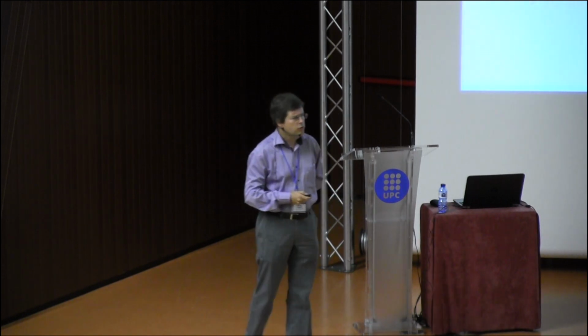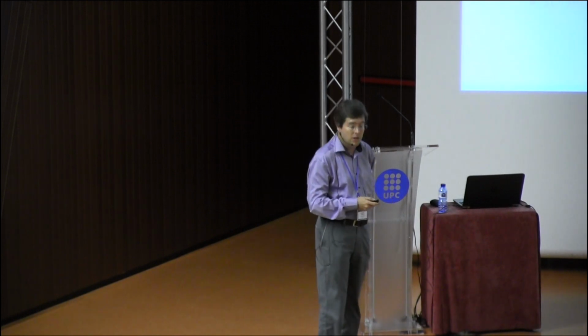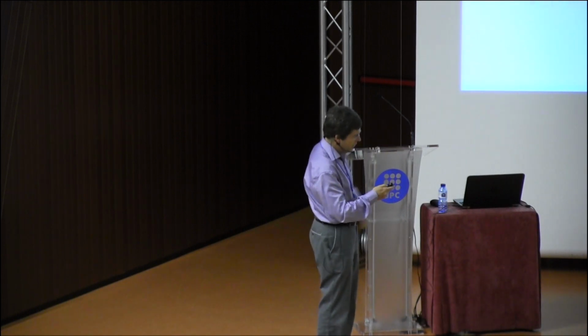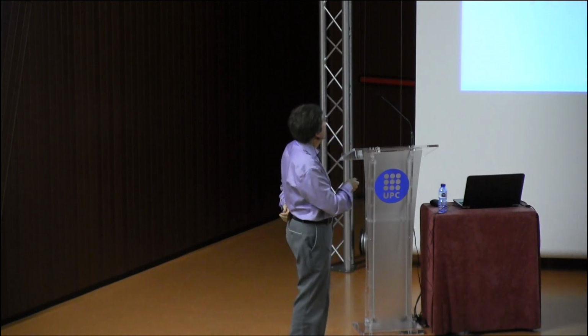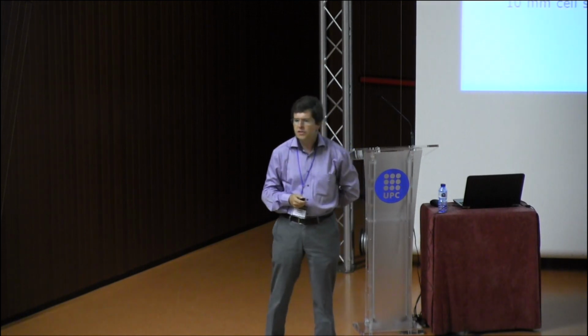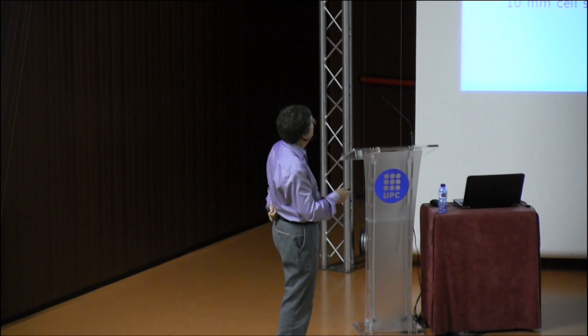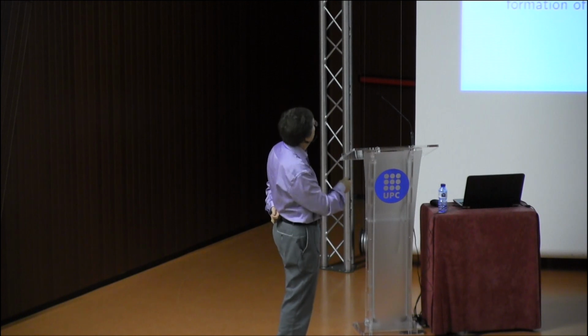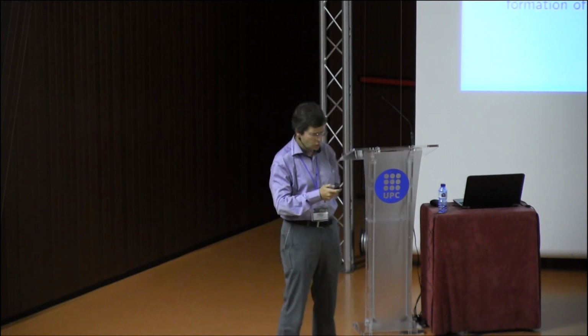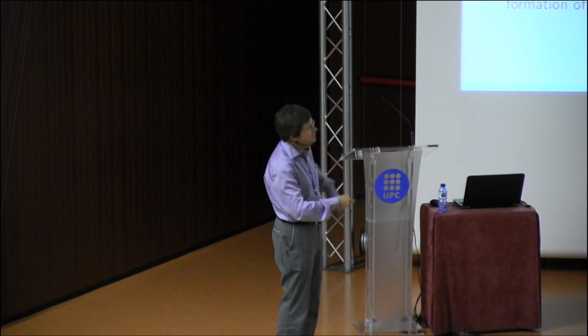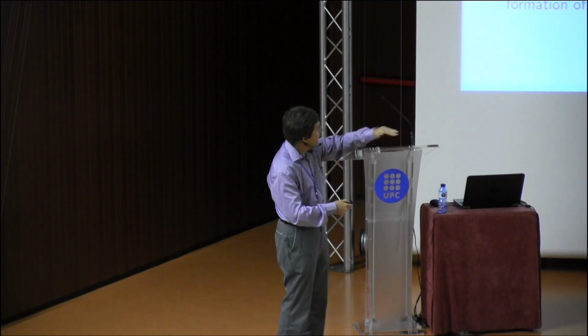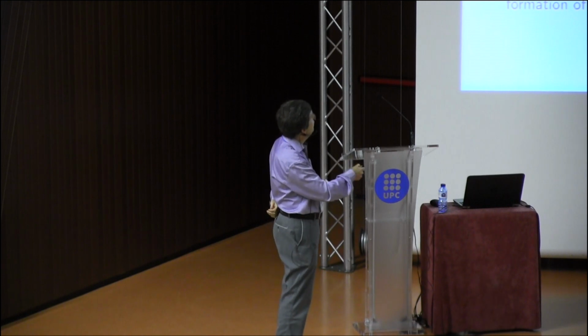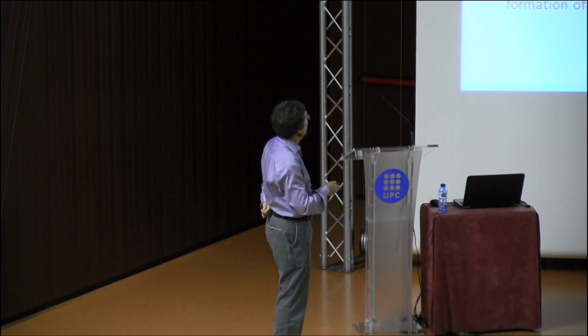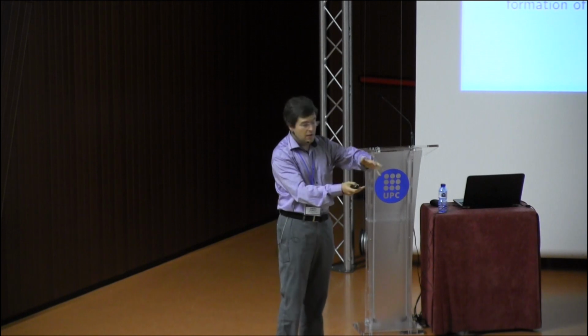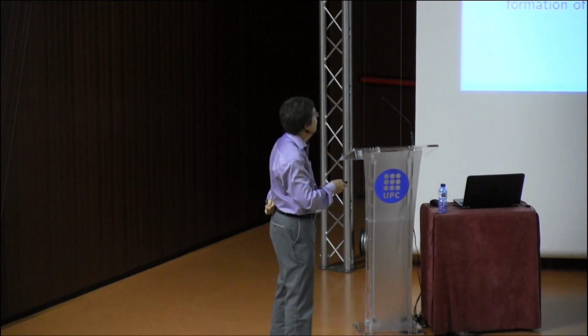This phenomenon is also present in porous materials, not in the form of Luder's bands, but in the form of crushing bands. For instance, in these aluminum foams, which you can observe by X-ray tomography. If you compress it, you will not have homogeneous deformation. You will have a crushing band here. This time the band is not inclined, it's horizontal, almost, due to the crushing of the cells.